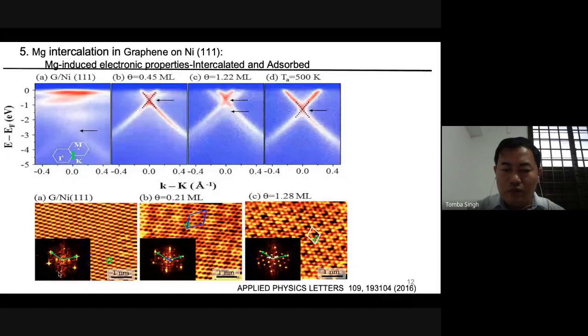Here we see the spots indicated by the green arrows. These correspond to the carbon atoms of the graphene. The unit cell is drawn here. At low coverage, we spotted new spots shown by the small blue arrows. The unit cell is shown here, so this belongs to the intercalated case. But if we introduce more, then there are both the intercalated and the adsorbed cases. That's why the spots of the adsorbed case are visible.